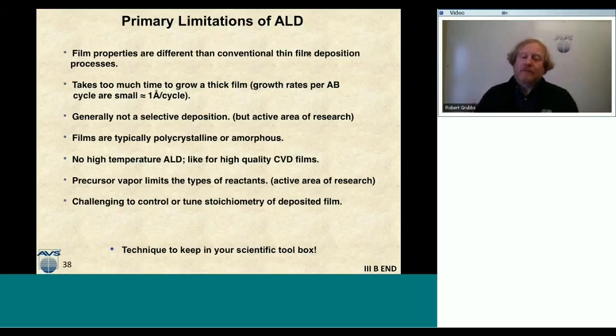So there's all sorts of materials we can deposit with ALD, but that really comes back to the type of precursor that we use, whether that's a solid, a liquid, or a gas. And if it's a solid, we need to get that vapor pressure up and into the reactor to have it undergo ALD chemistry. And so there's all sorts of chemists, organic, inorganic, and organometallic chemists, working on new precursors that have high vapor pressure, that are thermally stable, and perform the ALD chemistry that we're looking for.